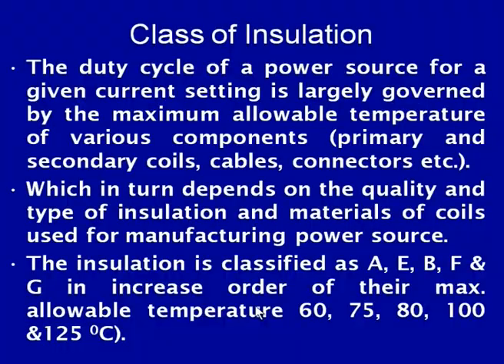There can be different classes of insulations and they will have different capabilities to withstand different temperatures. Say insulation is classified as A, E, B, F and G. These are in increasing order of their maximum allowable temperature. Say A for 60 degree centigrade, E 75, B 80, F 100 and G 125 degree centigrade. So, the A class insulation will have the maximum allowable temperature of 60 degree, so it will have minimum resistance to the heat, while the maximum resistance to the heat and temperature generation will be offered by the G class insulation, which can withstand up to 125 degree centigrade. So, in terms of the duty cycles, the A class insulation will allow us the lowest duty cycle and the minimum current, while the G class insulation will allow us to go for higher duty cycles even with higher welding current.